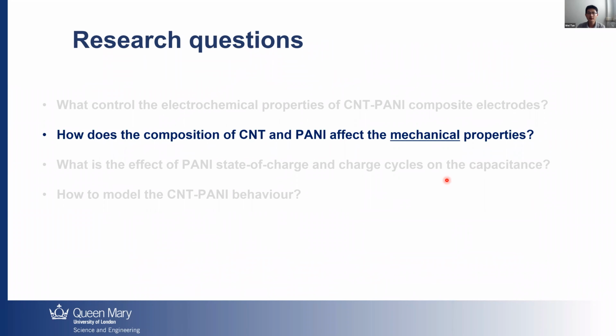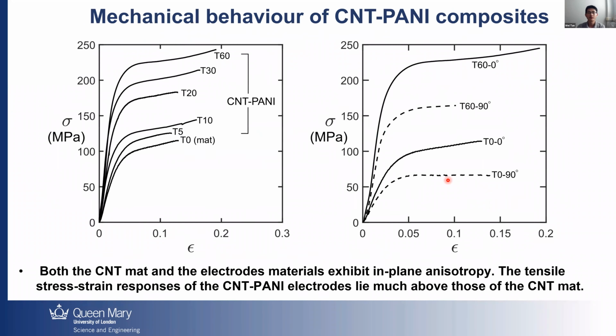The second question is, how does the composition of CNT and PANI affect the mechanical properties? In this mechanical part, we have categorized the mechanical performance. We conducted several different tests, from just the bare CNT mat to the CNT-PANI with the highest amount of PANI. And we see increasing strength and stiffness. We can also see some anisotropy when we test the material in the longitudinal direction and the transverse direction.